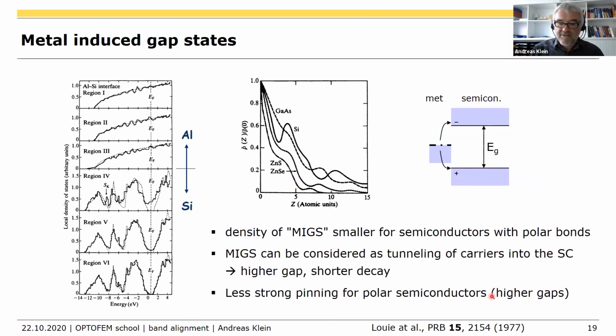So that's just an old calculation. This is by Louie et al. from 1977. So that's the interface between aluminum and silicon. So down here is the silicon. You see here, this is the band gap. That's the density of states. Here is the band gap. This is the aluminum, which shows more or less a square root density of states as for a free electron metal. If you go to the interface, you see that there is no more a band gap. The gap is filled with states. So this is a density of states which is resolved layer by layer across the interface. Okay, so these are these induced gap states.